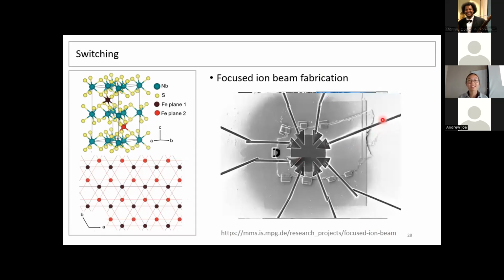Okay, so here's an example of one of my devices. This is like the edges of my crystal. It's a sort of irregularly shaped thing. These little rectangles are where I've deposited platinum. Everything that looks white is gold. So basically the platinum is there to connect the gold on top of the crystal to the gold not on top of the crystal, so I can have a nice conductive path all the way out to where I'm connecting wires.